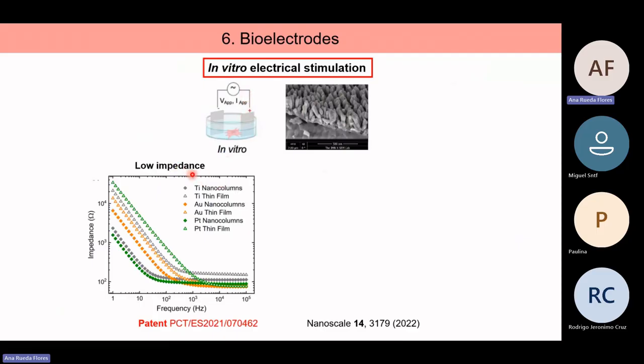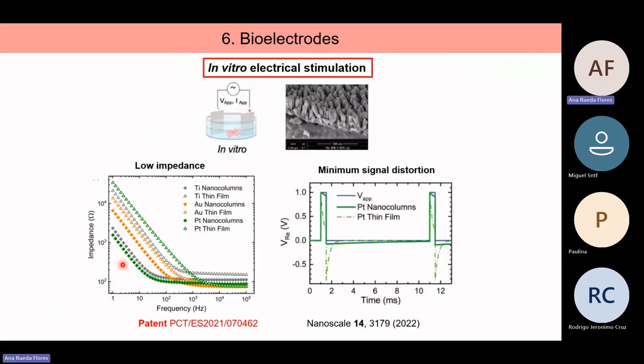We have done the study for 3 different metals: gray for titanium, orange for gold, and green for platinum. Closed symbols are the nanocolumns, open symbols are the thin films, and this is the impedance spectra in logarithmic scale. So you can see that for the 3 metals, the nanocolumns exhibit much lower impedance than the flat thin films. And this is good because it means that you can perform electrical stimulation with lower currents. If you have lower impedance, you can apply lower voltages. And the other good thing is that we can transfer the electrical signal more faithfully.